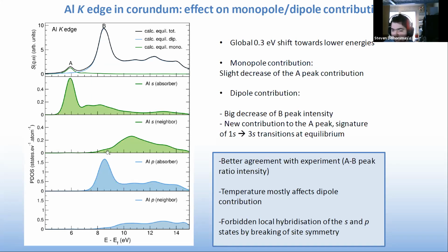Here we have a centrosymmetric aluminum site, and so it's a given, I would say, that we are not seeing any P states here on the signature on the S states. And so the effect of the vibration, by breaking local symmetry, is to enable this forbidden contribution to appear. So this was globally for the XRS aluminum K edge in corundum.